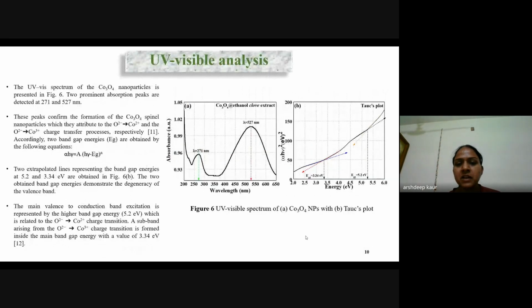This is the UV visible analysis of the obtained synthesized particle. In the UV visible spectrum, we have seen two absorption peaks detected, one at 271 and the other at 527 nanometers. These peaks confirm the formation of Co3O4 spinel nanoparticles, where the first peak shows the O2- to Co2+ and the second one shows the O2- to Co3+ charge transfer process.